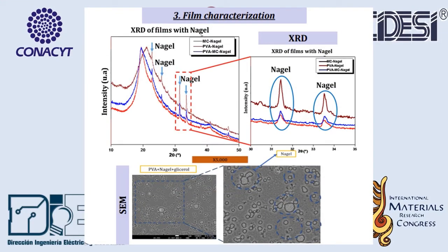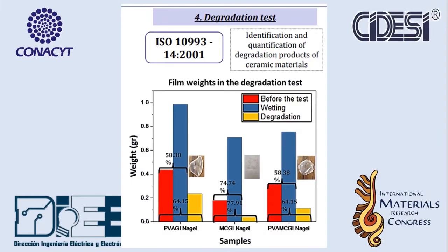Thanks to the XRD characterization of the membranes, the presence of peaks corresponding to the Nagelschmidtite particles was found, and by SEM, it was possible to confirm the presence of particles in the polymer matrices with a distribution throughout the membranes. The degradation tests showed the methyl cellulose membranes were not suitable to be used as dressing as they degraded completely after 5 days. However, PVA-G and PVA-MC membranes with and without Nagelschmidtite particles showed an absorption percentage above 50%, indicating the ability of these membranes to absorb exudates.